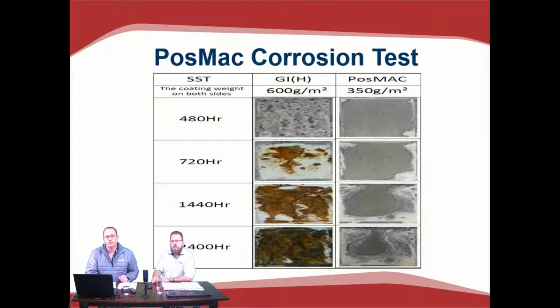I did a small test here for you guys to just show a basic experiment which was done between our POSMAC sheets and a hot dip galvanized sheet. A salt spray test was done over a period of time with a constant 5% sodium at 35 degrees Celsius. That is basically like building this tank in the waves of the ocean because of the salt that was sprayed on it constantly. As you can see in the picture, the POSMAC shows 5 to 10 times the corrosion resistance compared to galvanized on flat sheet surfaces.